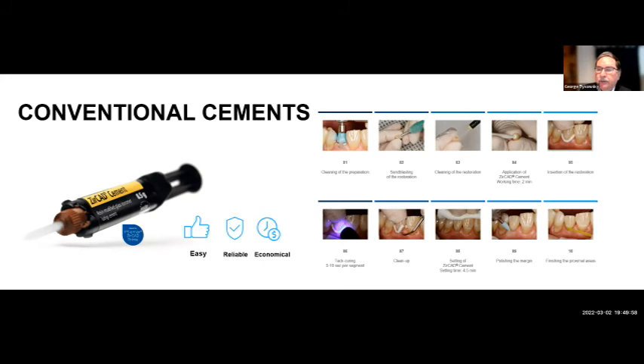So we clean the preparation, sandblast the restoration, clean it off, and now you're just going to apply the ZrCAD cement, inserting it, letting it set up, tack it for 5 to 10 seconds per segment as we did, cleaning it up, and then let the set time and then finish and polish and complete the restoration. So the easiest and most user-friendly of all the cements, again, but the weakest bond of basically retentiveness.